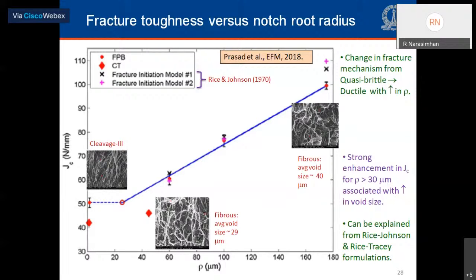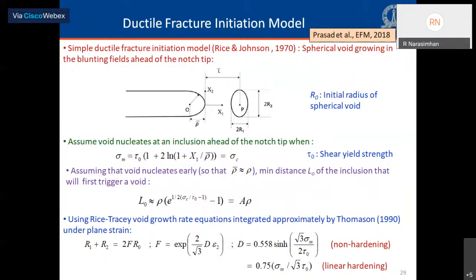We used a simple model based on the classical Rice-Johnson theory and coupled it with the Rice-Tracey void growth equations in order to predict this experimental trend. And the predictions are shown here by the plus symbols, and you can see that the predictions match with the experiments pretty well. Here is how the model works. Very briefly, the Rice-Johnson model involves the growth of an initially spherical void of radius R0 in the blunting fields ahead of a notch tip.